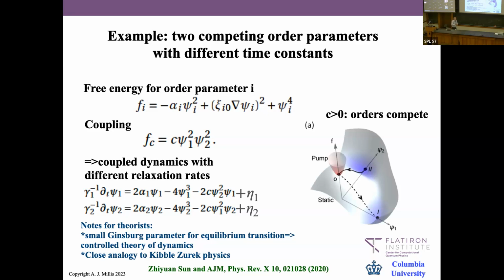Now what I want to argue is that the ultrafast experiments, which dump some energy into the system, basically first rapidly heat the system up to a high temperature because you put a bunch of energy in. What that means is you take this free energy landscape and you roll it up into a single minimum at 0. That's what this thing here is supposed to do. Then as time goes on, this thing unfolds into the 0 temperature energy landscape, which is this. And we want to ask, in that time-dependent energy landscape, how do the order parameters move?